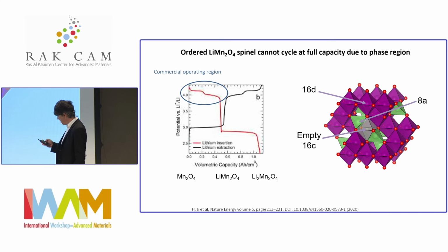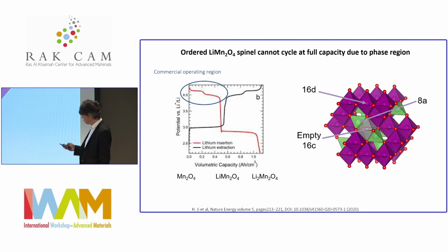So again, back to physics courses, I had sort of learned that with disorder, you could reduce first-order transitions to second-order transitions, and in some cases even remove them. And that's what we try to do. Could we introduce spinel disorder between the 16D and 16C sites? These are nominally empty in a spinel, and these are filled, to actually kill this first-order transition and make it second-order or make it disappear at all.